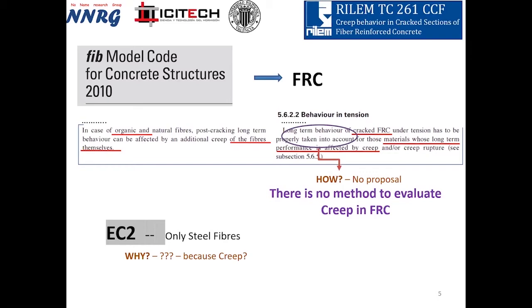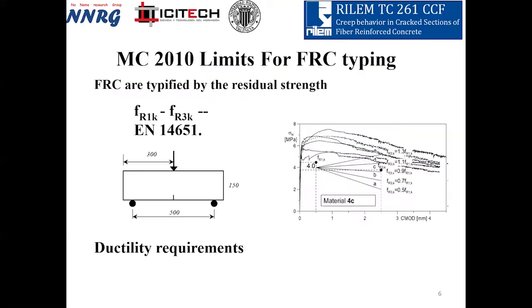There is no criteria to apply creep in fiber reinforced concrete, nor if it is synthetic or steel or another type of fiber. And this, even when we talk about the Eurocode 2 that is coming, in this case, only steel fibers are accepted and the others not. Why? Maybe because we continue with the warning that we have no experience, or we are in panic thinking about creep. Well, fiber reinforced concrete usually is characterized by a flexural test in a notched specimen and defines two parameters: the residual strength after cracking in this specimen at a low crack opening, 0.5 millimeter, or a long crack opening, 2.5, thinking on serviceability or ultimate limit state.